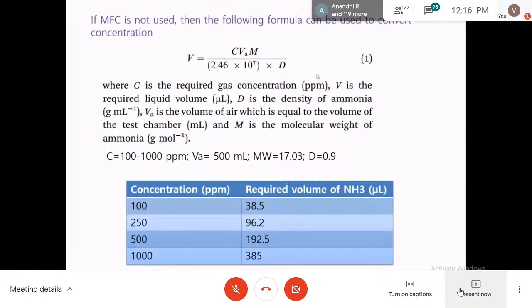So this is the formula we used to calculate how much liquid is required for making the corresponding concentration. If we want to make 100 ppm of ammonia, we should use 38.5 microliter. Similarly, for 250 ppm, we have to use 96.2 microliter. So we vary from 100 to 1000 ppm, and then we check the electrical response. This formula connects the density and volume of the test gas liquid required, and the molecular weight and everything.